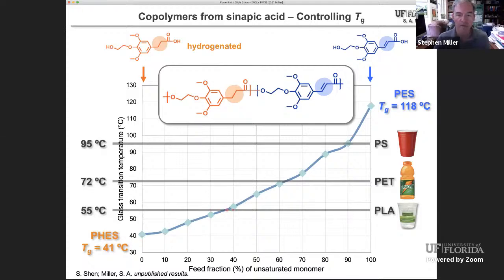If you have about a 30% degree of double bonds still present in the backbone, you get to match the glass transition temperature of PLA. If you have about a 60% presence of the double bond in the backbone, you get to match the Tg of PET. With a 90% presence of the double bond in the polymer backbone, you get to match the glass transition temperature of polystyrene. So you get to tune the glass transition temperature from the same bio-based molecule.